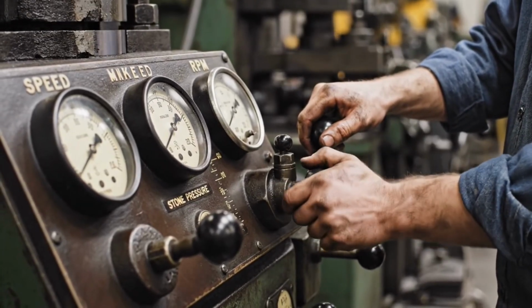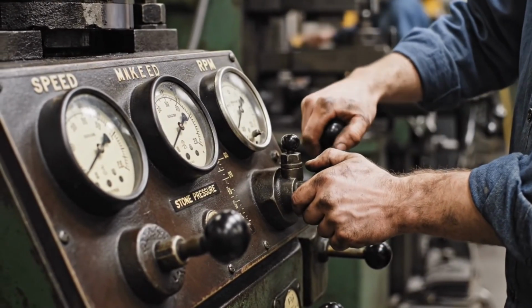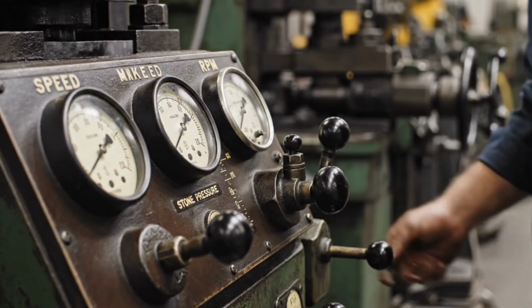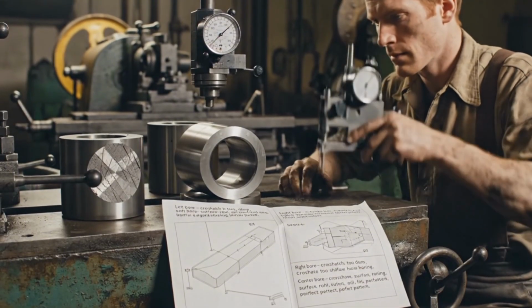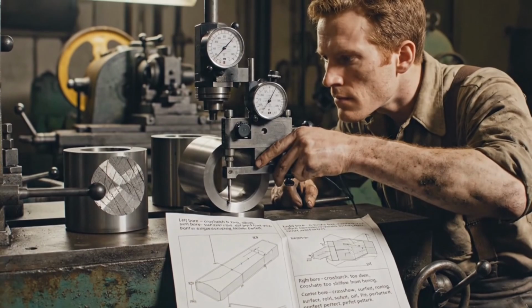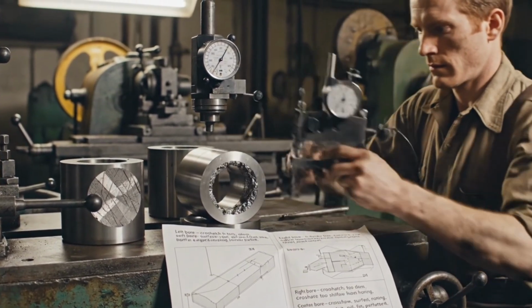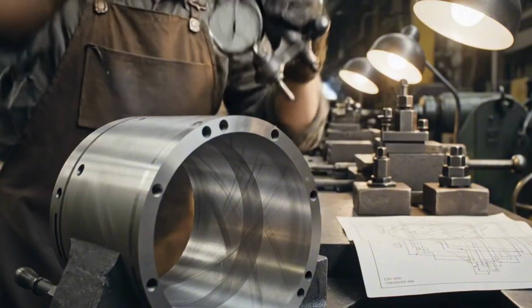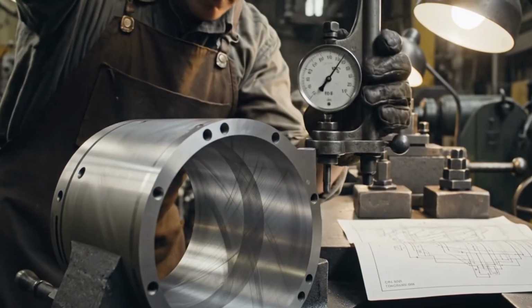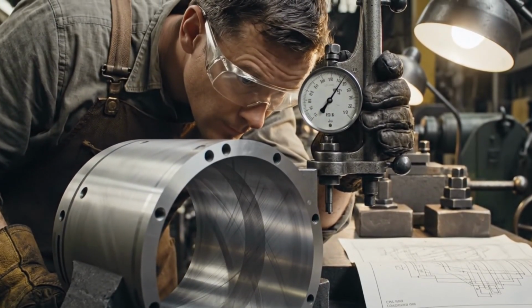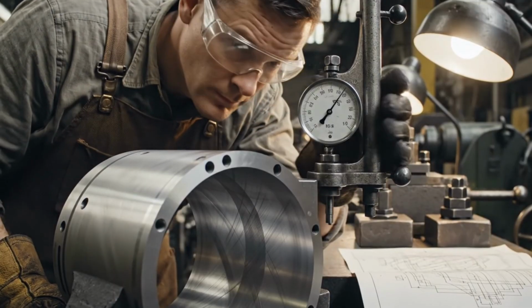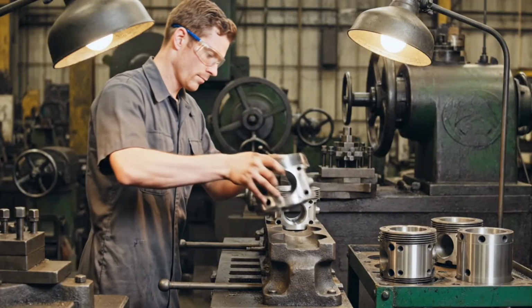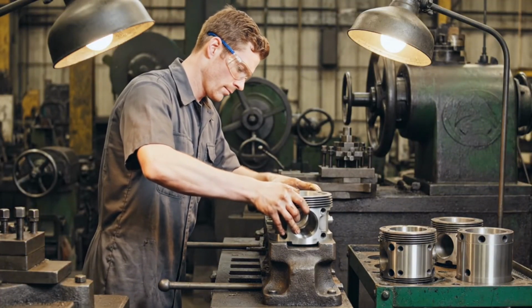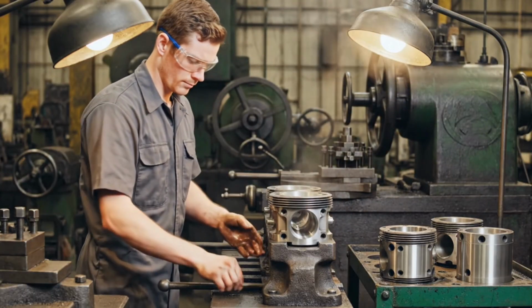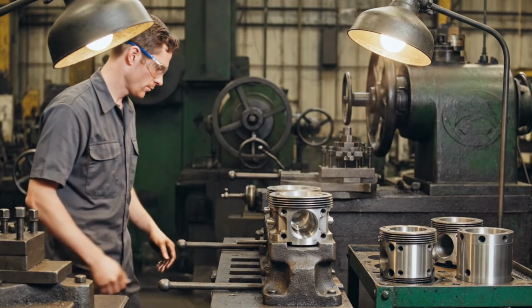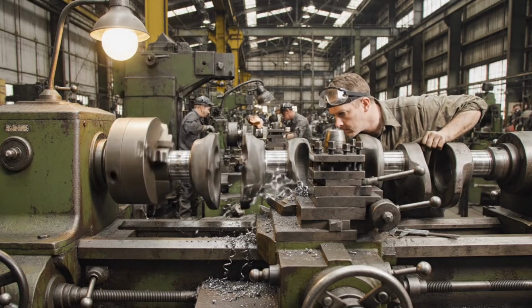Getting it right required careful control of the honing speed, the pressure of the stones against the bore wall, and the length of each reciprocating stroke. Too aggressive, and the bore became oval. Too gentle, and the surface remained rough enough to accelerate wear. Each cylinder was measured after honing with a bore gauge, checked against the engineering specification, and if necessary, returned to the honing machine for another pass. There was no shortcut here. Each cylinder bore had to be correct.